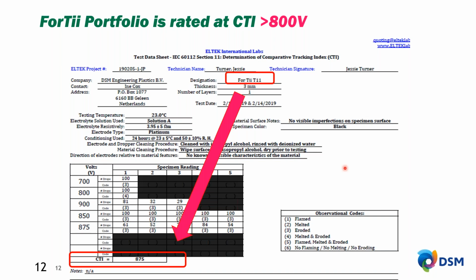So as voltages increase, especially for electric vehicles, CTI becomes more and more important. Many are looking for very high CTI ratings so that there's no danger of arcing even at high voltages. The ForTii material boasts a CTI rating of greater than 800 volts, and that's really best in class in the industry for the family of materials that can survive the reflow soldering process.